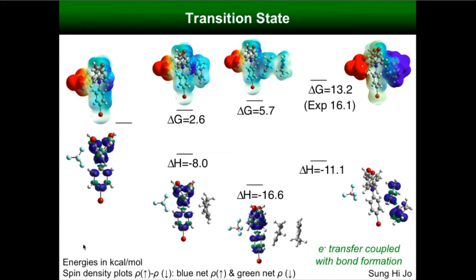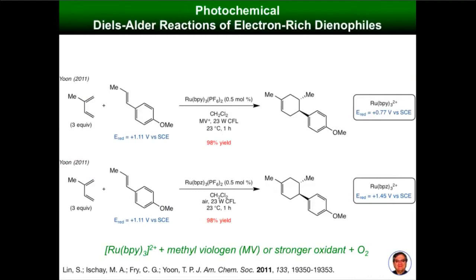So another example of a Diels-Alder type reaction, which has been done with photocatalysis, is to react isoprene with anethole. You can make this with a ruthenium catalyst, with good yield and high diastereoselectivity. This is work out of the Yoon lab. But coupled with that, there's this methyl viologen auxiliary agent that's there in stoichiometric quantity. Methyl viologen, you may remember, is paraquat. Paraquat is somewhat toxic. It's a herbicide, probably not the best thing to have around.